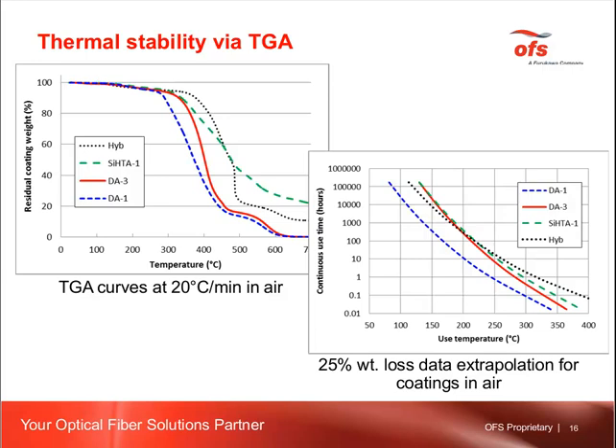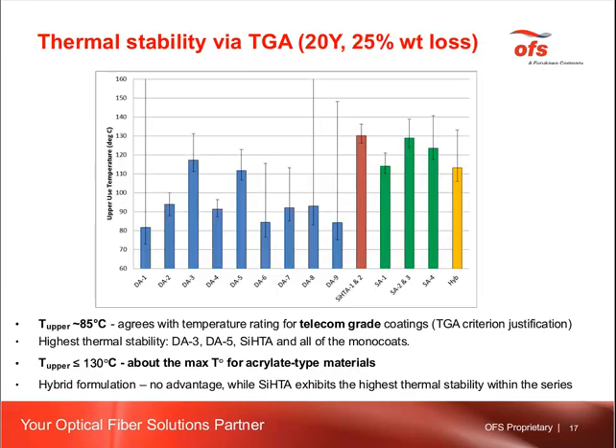And on the right-hand side, there are examples of the data that we obtained using the TGA method. So they correspond to the 25% weight loss criterion, and the x-axis is the use temperature, and the y-axis is the continuous use time. These two parameters are correlated to each other. I'm going to explain it in some detail a little bit in a couple of slides.